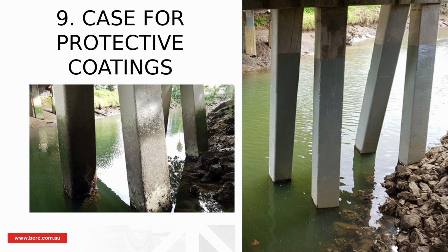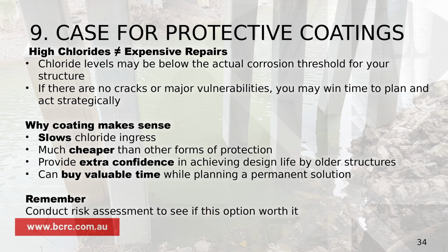And I would present a few cases here. On these pictures you'd see newly applied coating, probably about 3 meters high, and the same coating on the left 1 year after, still intact with some marine growth on it. When you're dealing with high chlorides, especially once you already tested, it doesn't necessarily mean that your structure is done and there's not much you could do about it. And it doesn't necessarily mean expensive repairs, because your actual corrosion threshold could be higher than these levels. And you might still have some time, especially if you have no cracks or other vulnerabilities on the structure. Coating might give you that time to plan and budget for the next stage.